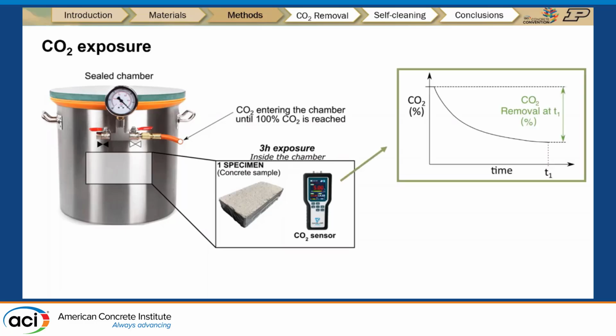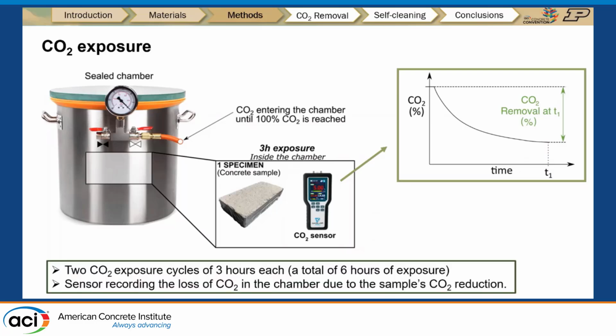carbon dioxide sensor. Then we can see that over time, the carbon dioxide concentration will go down. There will be 2 carbon dioxide exposure cycles of 3 hours each, a total of 6 hours of exposure for each sample we did. And the sensor will record the loss of carbon dioxide in the chamber due to the sample's carbon dioxide reduction.